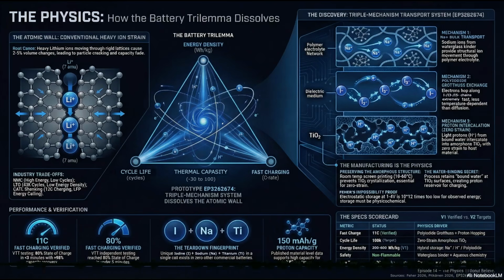Worse, that plated lithium grows into dangerous, needle-like metallic structures called dendrites. I've seen pictures of those under an electron microscope. They look like sharp little metallic stalagmites growing inside the battery. Yeah, and if they grow long enough, they pierce right through the separator, short out the battery, and cause a catastrophic fire. Which naturally leads us to the third conflict in the trilemma, cycle life versus fast charging.